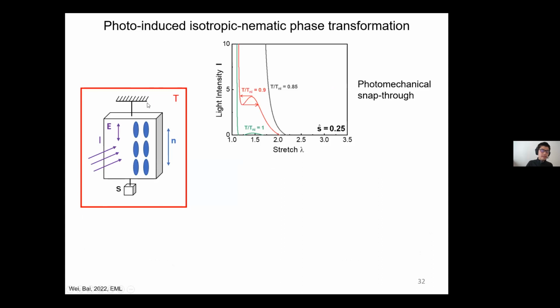So what we did is we can still study this example, and then we increase the light intensity and record the stretch, okay? At a certain temperature and stress, you see that it increases to some peak. And because of the first order phase transition, it snaps. So you see a snap-through instability, but it doesn't happen all the time, right?